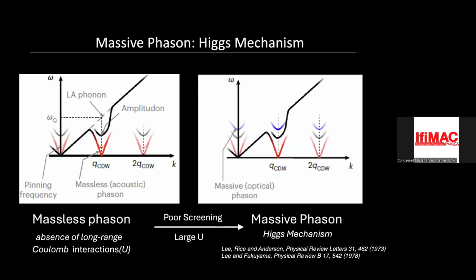And in fact, what happens is because of the interaction with these Coulomb forces, and here's the Higgs mechanism, the charge density wave excitations interact with the Coulomb forces, and this massless phason, this one, really becomes massive. So it's no longer seen at zero frequency. It has a finite frequency. The lowest energy that you need to excite this mode is actually finite. So you need some energy to excite the phase mode. That's what happens when you have these strong Coulomb interactions.